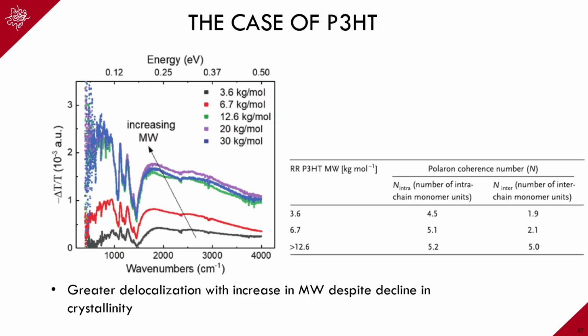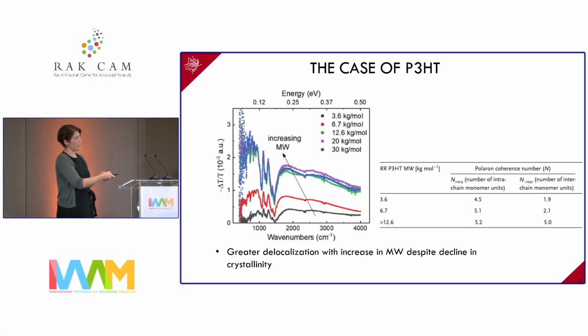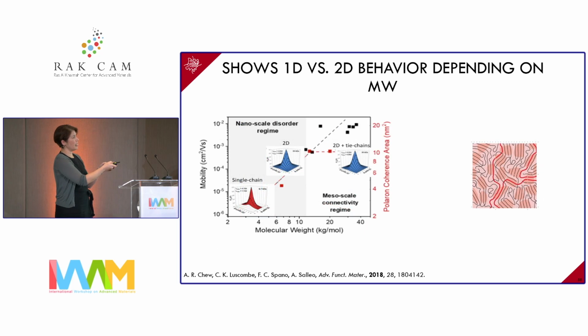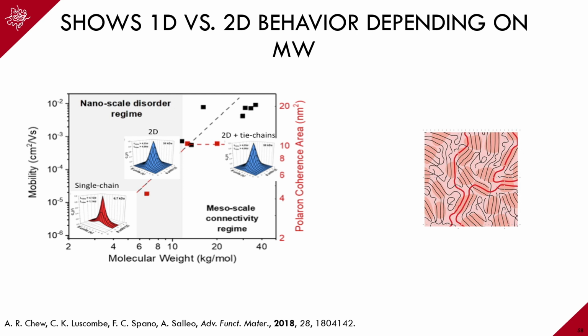And in particular, what we saw was a molecular weight dependent behavior. So when you have very short molecular weights, the degree of delocalization is primarily within the chain and not much delocalization in the pi-pi stacking direction. If you increase the molecular weight, that behavior changes now. Now you have delocalization in the chain, but also you start to see delocalization in the pi-pi stacking direction. So this kind of confirms what we typically draw, which is the following. When you have short chains, it's 1D behavior, but when you get to longer chains, it's 2D behavior, really highlighting the role of the crystals.